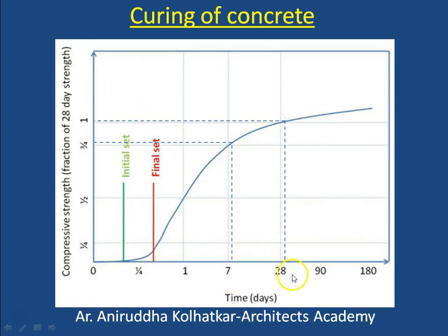Now this graph is showing you how the strength of the concrete develops over time. Here you can see on the Y axis the compressive strength which is developed, and on the X axis the number of days after casting. As you can see, after casting of concrete, the concrete slowly starts developing its strength till it attains the initial set, then the final set, and then it goes on developing strength up to day number 7, where it has already developed a strength which is 3/4 of its final strength, meaning it has already reached more than 70% of its strength. Then it further becomes stronger, and at day 28 we can say that it has achieved its final strength. Though you can see that concrete is still gaining strength, the strength which we consider to be the final strength is after 28 days.